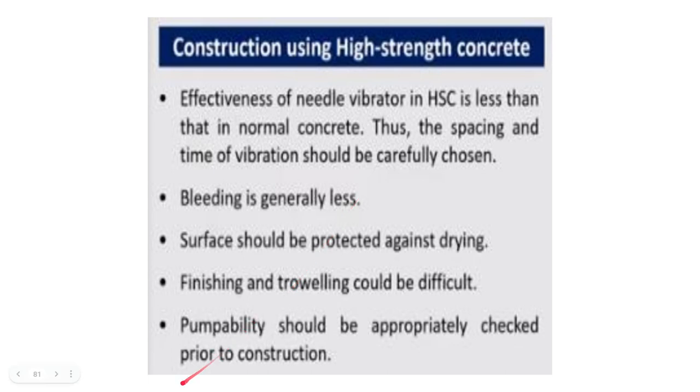Bleeding is generally less because of the low W/C ratio. The surface should be protected against drying. Finishing and troweling could be difficult. Pumpability should be appropriately checked prior to construction. All of these factors are mainly because of the lower W/B ratio, which is less than or equal to 0.3.